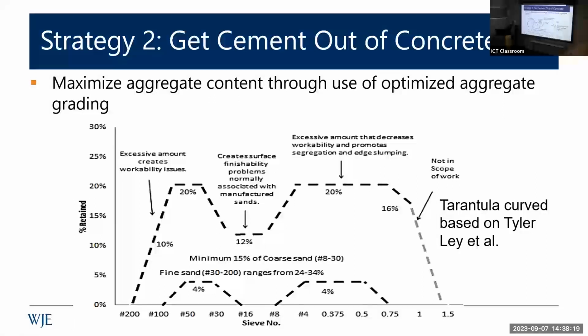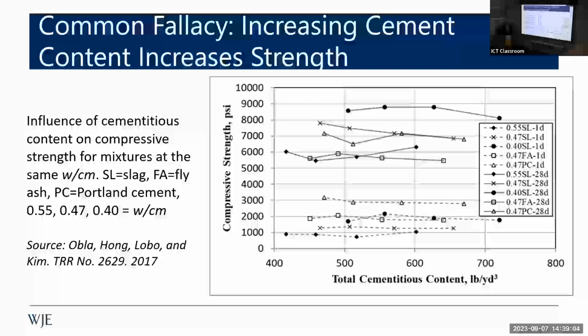You can see the tarantula, right? In Tyler's mind, this is a tarantula. And this has been an amazing tool for slip form paving concrete that has to be able to mobilize and consolidate under vibration. And then as the vibration passes, it sits there and will stand up straight and tall. But what you get right down to, the similar tools that you have become used to with VMA, I think, Jeff, you were saying for your RCC work, you're actually looking at VMA. Same concept, right? Just enough void. We identify the voids, we reduce them, we put enough binder in there to fill the voids and a little bit more to provide the lubricity needed. And so these are our tools that we're using.